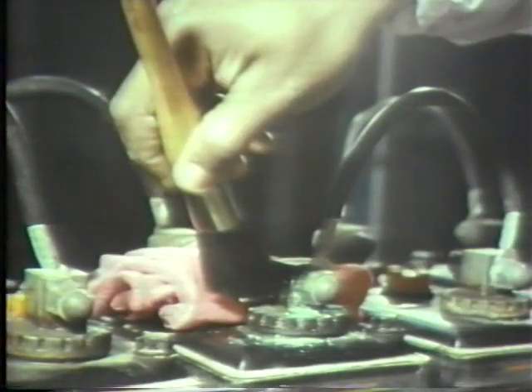Corroded terminals like this one can create additional resistance between cells and keep the battery from getting a good charge. To clean a corroded terminal, first scrape off the flaky corrosion, being careful not to short across the cell terminals. Then brush away the powdery residue and dispose of it properly. The cell's vent cap should be covered with a rag to keep from contaminating the electrolyte inside.